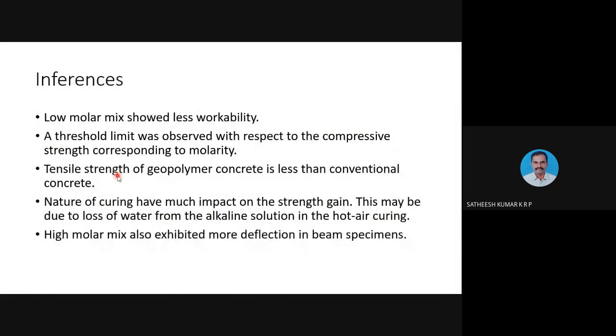And with respect to the high molar mix, these mixes exhibited more deflection in the case of beams. So from this, we are trying to get the ductility of the material, because high molar solution, in the sense only the alkaline component is changing. We are not actually changing the fly ash ingredient. Only by increasing the alkaline reactors, the behavior of the material is found to be towards ductility rather than brittle material.